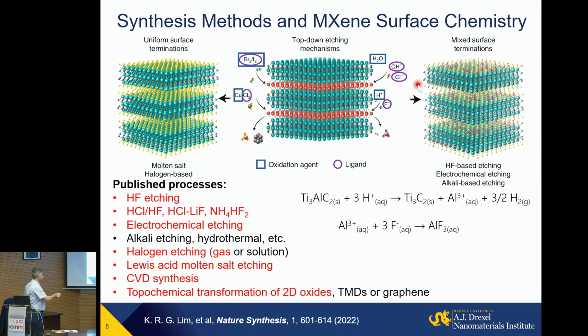What happens when you do it? The transition metal picks up oxygen, hydroxyl groups, fluorine, whatever else is in the etching solution. And now there are weak van der Waals and hydrogen bonds, with water molecules and ions in between. And those materials can be delaminated, just like, for example, clay or graphene oxide, because the surface chemistry is similar in this case here. Nowadays, we have many ways to make it.